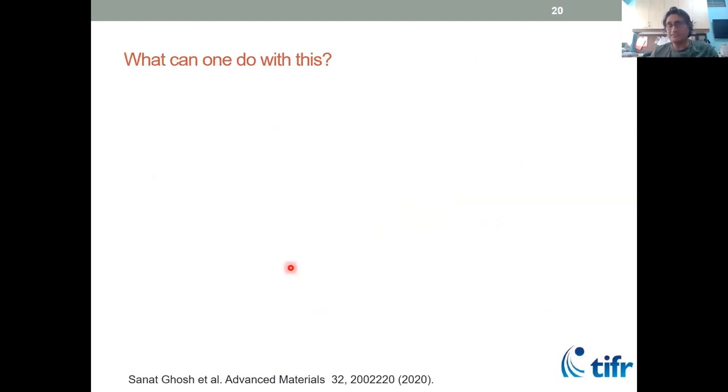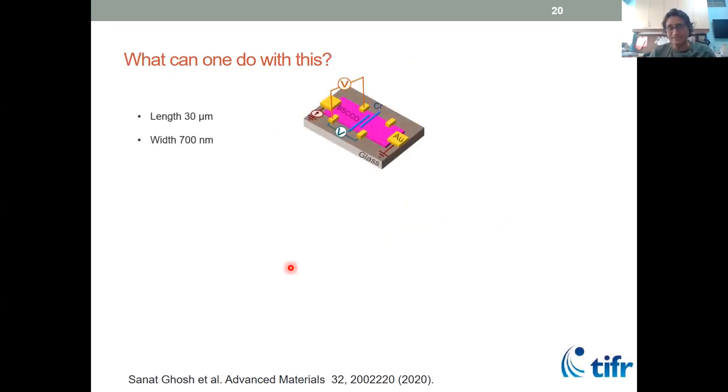So you might say, okay, what can you do with it? And so I'm going to show you some experiments. You can actually make wires which are very narrow, about submicron wide. The way to do it is you put two lines of chromium and you make the current flow through a kind of narrow path. These wires are submicron, something like 300 nanometers wide. They're about 2 nanometers thick, and then they can be microns long. Crystalline structure-wise, they're actually very good, okay?